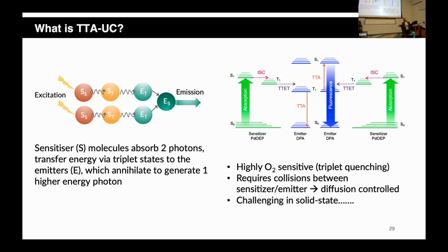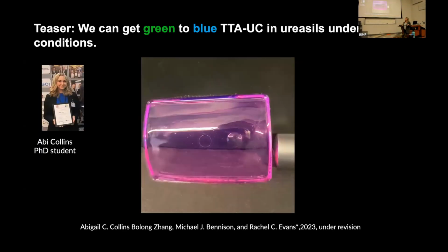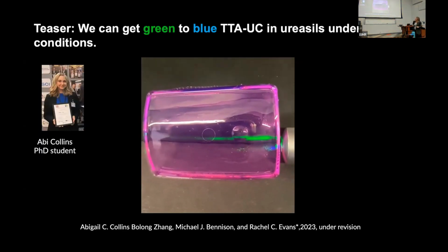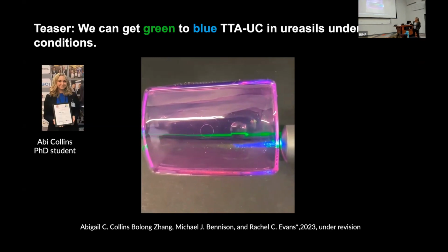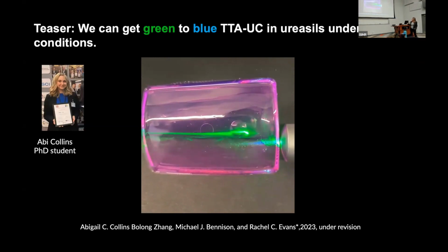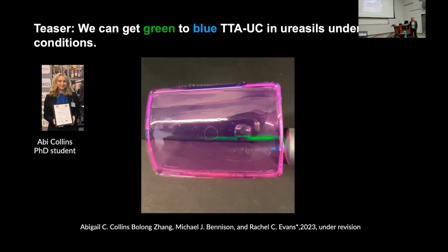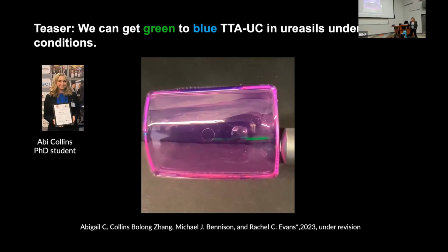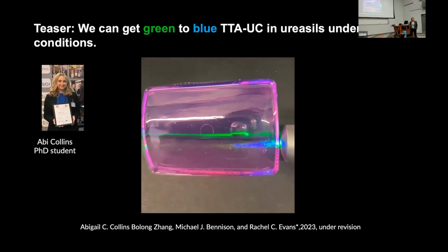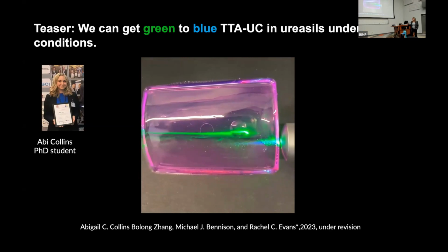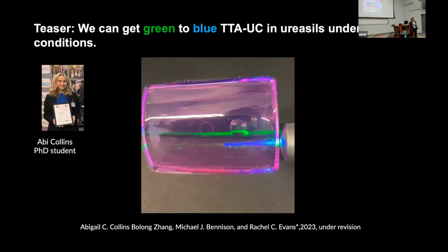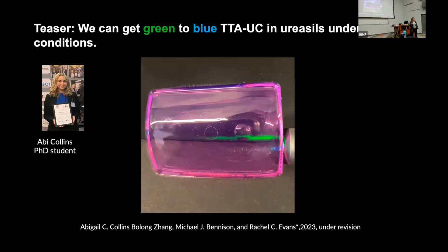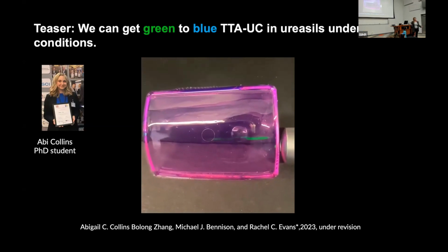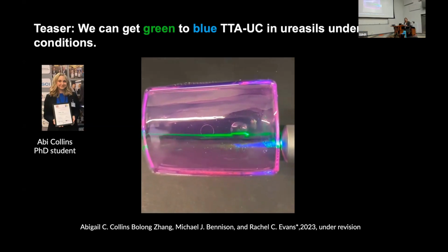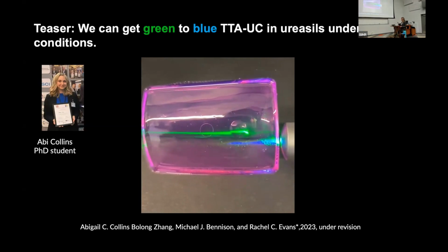And I'm going to jump ahead again and just give you a little teaser, because we've managed to do it in the solid state in our ureasils. So here we can see we're shining green laser light into our sample, and we're getting blue emission out in the solid state. There's no oxygen scavenger in there. We haven't removed oxygen at all. The ureasil itself has sufficient barrier properties to prevent oxygen quenching, but sufficient mobility within the matrix to allow these collisions to take place.